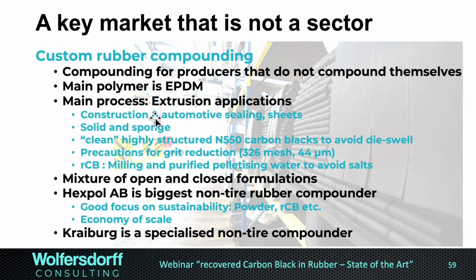We have a big pressure difference from inside the extruder to outside, and we have the die swell, which is a problem because then the mechanical structure of the profile cannot be maintained. And typically N550 carbon blacks are used to prevent that. Why clean?